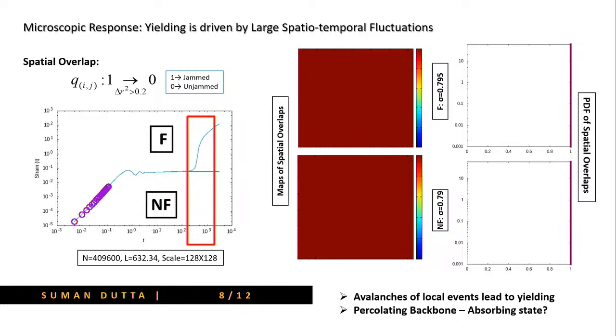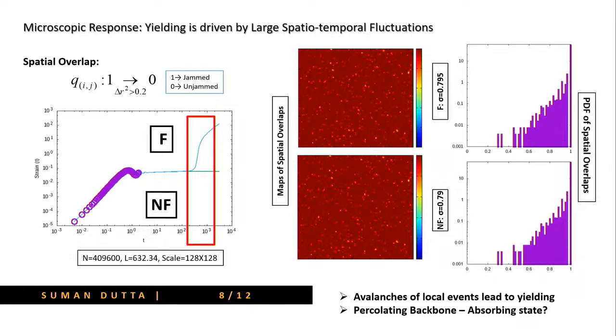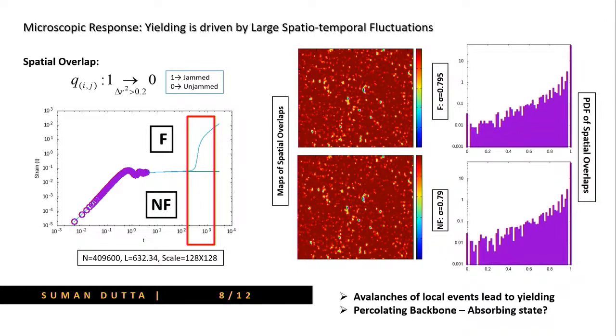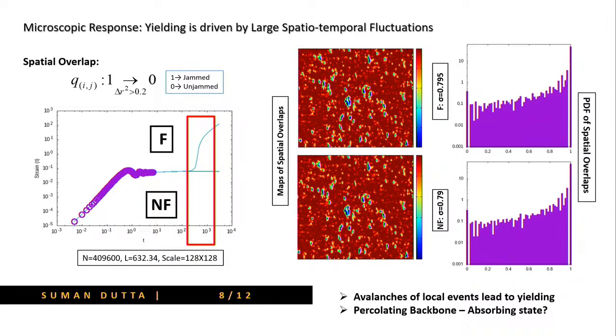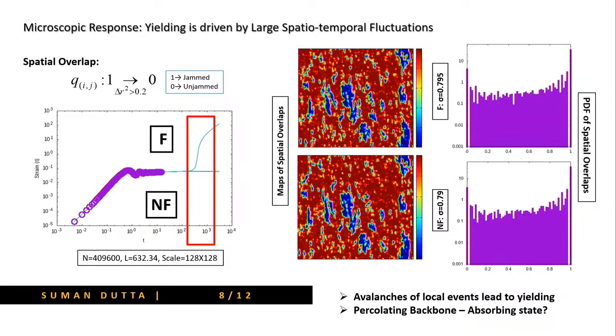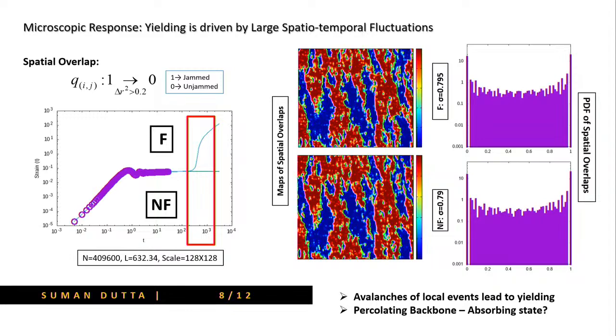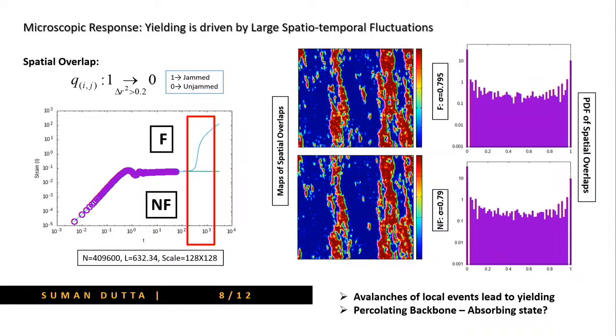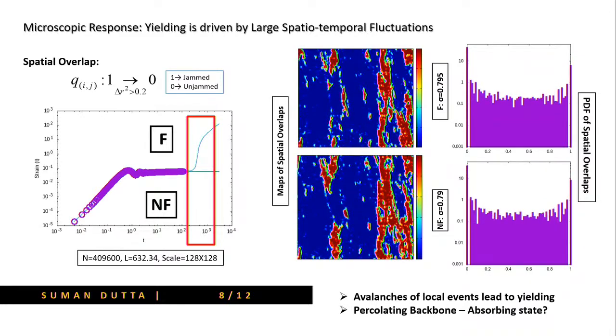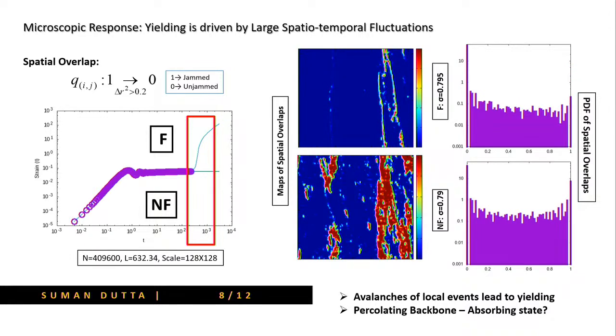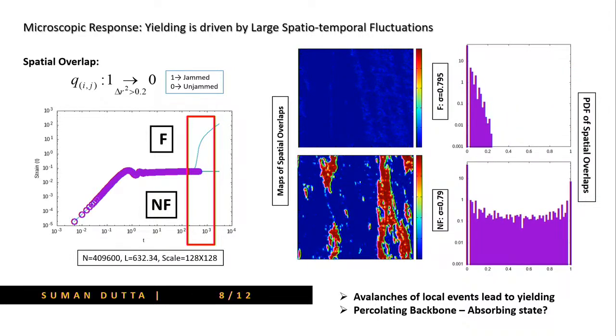So what we are showing here are the local fluidizations. If a zone has fluidized, it will turn from blue to red, or from red to blue, and if it remains stuck, it will be red. What we can see in the non-flowing case is a percolating backbone. Up to this point most things are identical, and for this non-flowing case you see this backbone, but here that backbone gets dilated and the system achieves a flow.